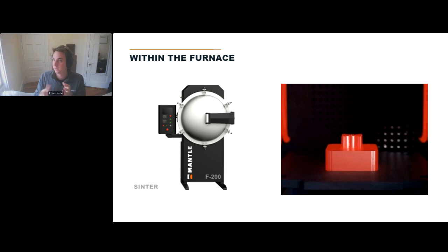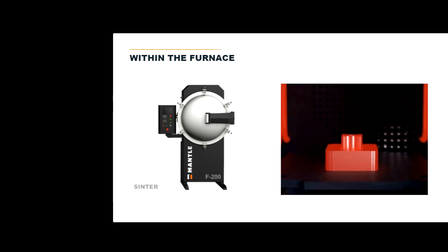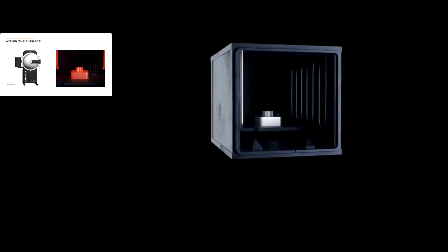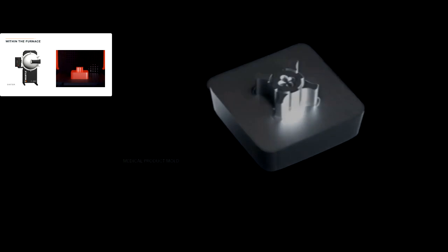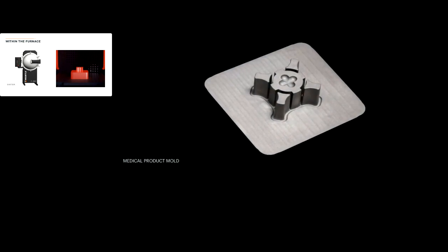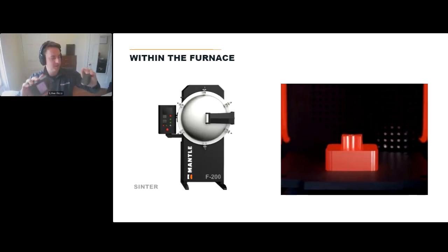This is, of course, where we lose our tolerance. It's great that we can machine parts to be as precise as we can get with a machining tolerance, but how closely can we predict that shrink is the challenge. But even with that, we're able to get plus or minus a thou per inch here. A little bit harder to get a camera into a high temperature sintering furnace that gets up to 1400 degrees Celsius. But a quick animation here just to see, it's almost like an oven, right? You stick the part in there, you hit start, and it's going to come out as a dense, strong metal part, as you can probably hear there.